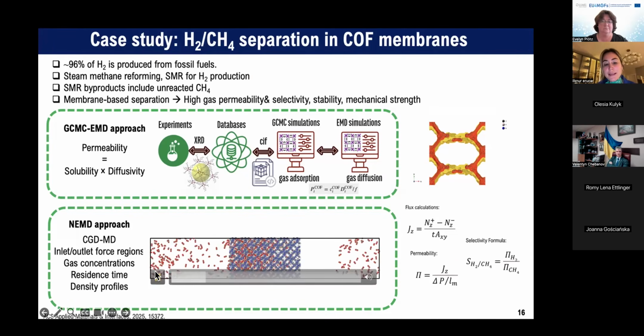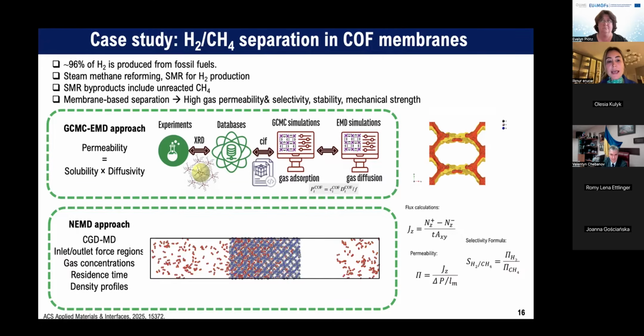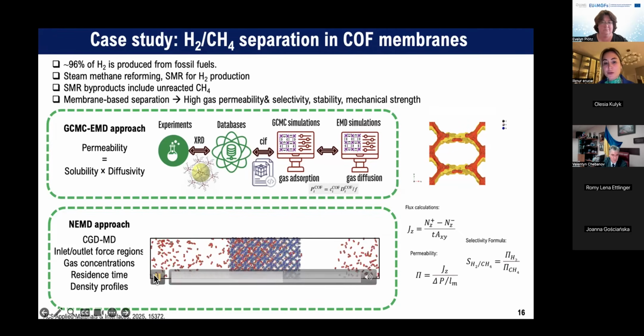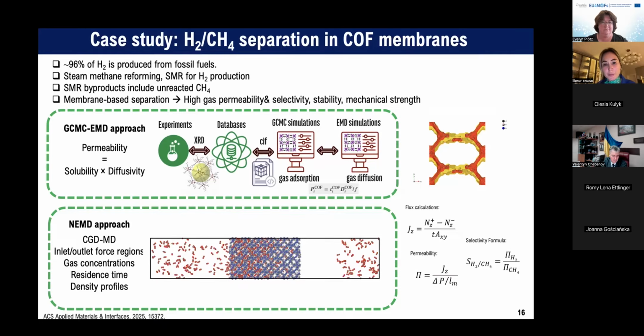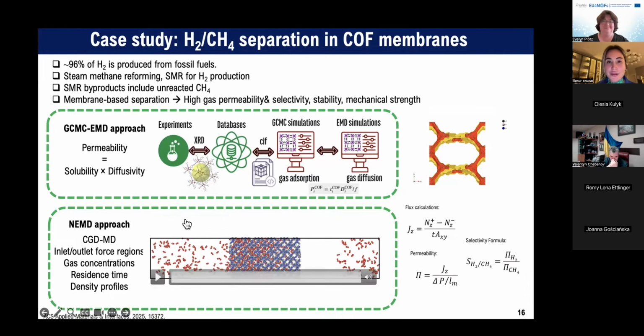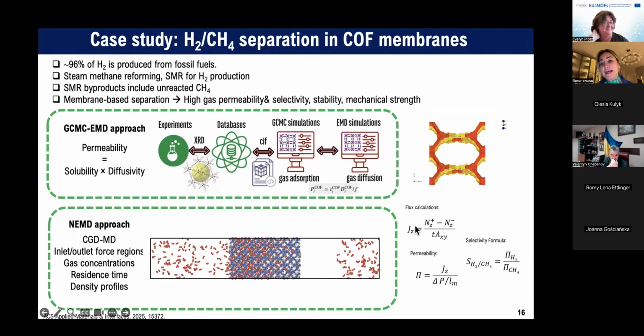Also, you can use NEMD, non-equilibrium MD simulations. Here you can see we create a whole membrane structure, and based on a gradient, here I have a concentration gradient NEMD, so gas molecules can pass through the membrane. This is a kind of realistic system, but the computational cost is, believe me, terribly high. So generally, that's why we perform the GCMC-EMD approach and then we switch to the NEMD method. Using the NEMD approach, you can directly compute the gas fluxes, counting the number of gas molecules passing through the membranes. Of course, you have to consider the area that you are modeling. And then you can switch to permeability and finally the selectivity.